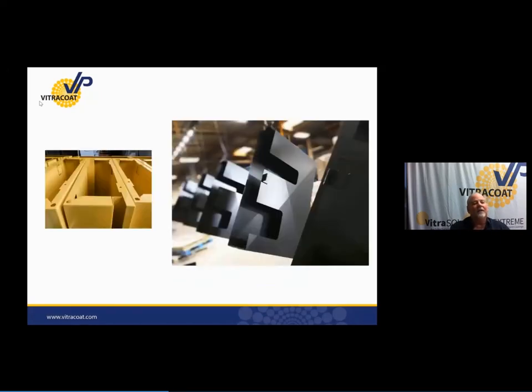Think about these parts. A lot of flat areas, a lot of edges as well. The most vulnerable area on these parts is going to be that edge. So you want to test the part. You actually want to test your worst case scenario where I've got the sharpest edge or the most edge, and then spray those through your system. Clean those through your process. Paint those with the powder that you want to evaluate and put those in salt spray.